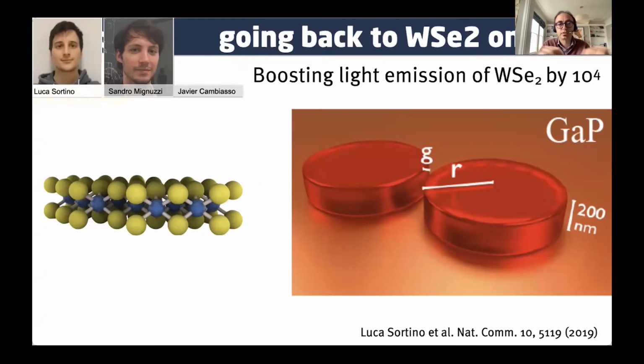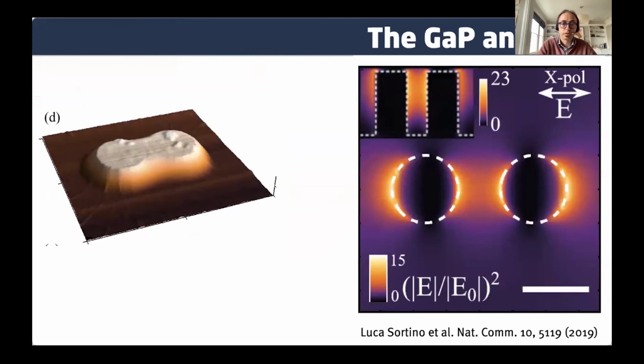So we took this two-dimensional material and then we placed it on gallium phosphide dimers that you see on the picture on the right. These are a few hundred nanometers in size, and we made them by electron beam lithography. And then we placed the 2D material on top. And doing so, you can see on the picture on the left, which is an AFM picture, we cover conformally the nano antennas.